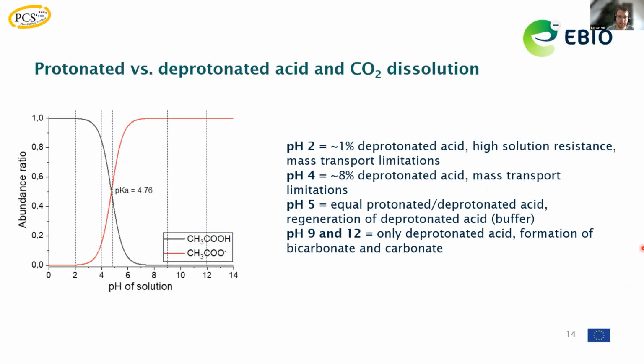And we've looked at two things. First of all, we were interested in what is the ratio of protonated versus deprotonated acids. And we could clearly see that around the pH where we could find the highest selectivity of Faradaic efficiency for ethane, we of course have a rather high amount of a deprotonated acid being present at the electrode surface, which is in very good agreement with the current picture that you have acetate ions being adsorbed at the surface.